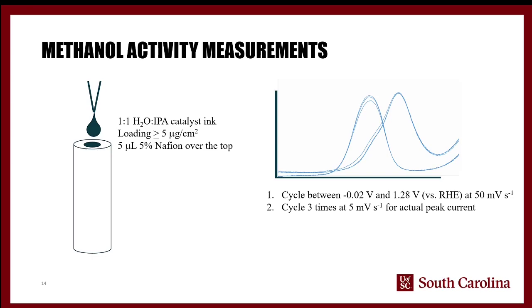And then we cycle 3 times at 5 millivolts per second, and that's where we actually pull our current and peak current information from. The reason we do it 3 times is we want to be able to pull an average number of at least 3 trials. In a lot of cases, we have more than 3, but 3 is sort of the minimum that we're willing to work from. And so what we're watching for is if you see a major decline during those 3 runs, then you know that something's going on. And so you either need to redo it and see if you can get a steady state, or you need to pay attention to how it's decaying over time, because that tells you that your catalyst is not stable.